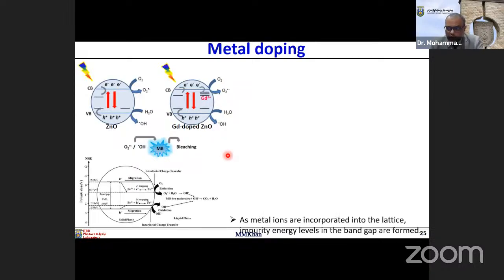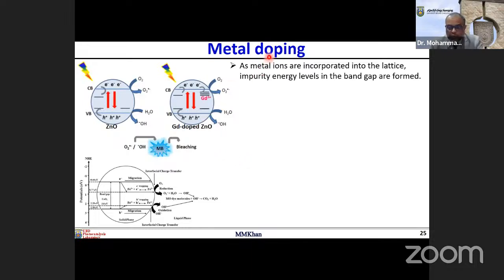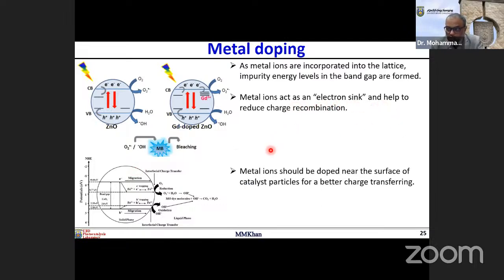For example, for metal doping, we can use different metals, maybe transition metals or rare earth metals, and based on your material and your dopant, you can get a different response from the material. As metal ions are incorporated into the lattice, impurity energy levels in the band gap are formed. So you can see here the different energy levels that will be formed, which will help in the migration of the electron from the valence band to the conduction band, as well as the migration of the charges. So metal ions act as an electron sink and help to reduce the charge recombination.